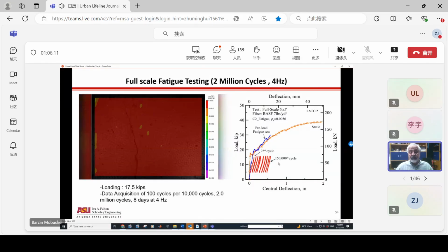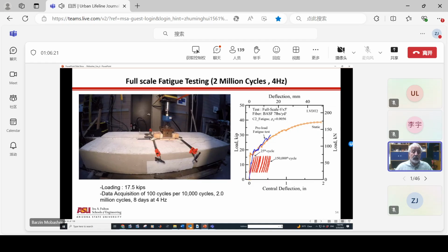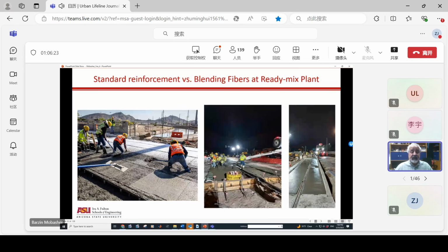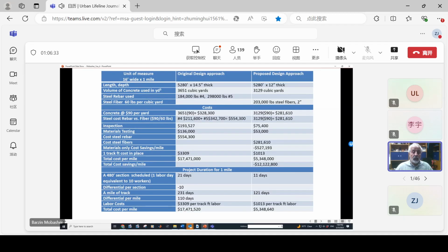So we continued this test for 2 million cycles, and here you can see the crack opening as a function of the cycles of the loading. And then basically they just switched over to the fiber case, and that way we got rid of the temperature and shrinkage control. What is interesting in this design, again, I'm running late on my presentation. If you look at the original design, per mile, the cost was $17 million because every single rebar had to be welded.